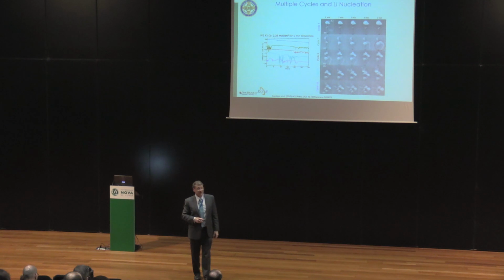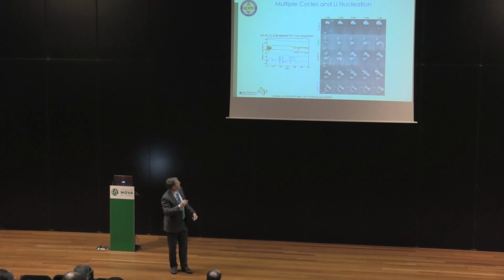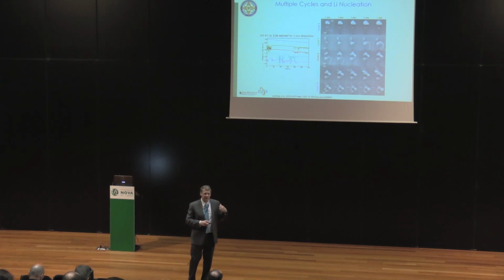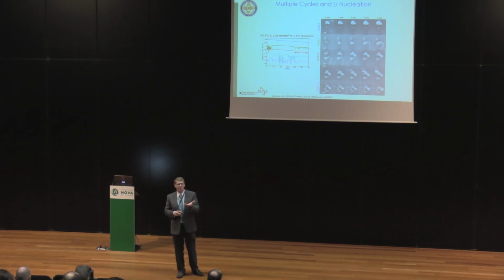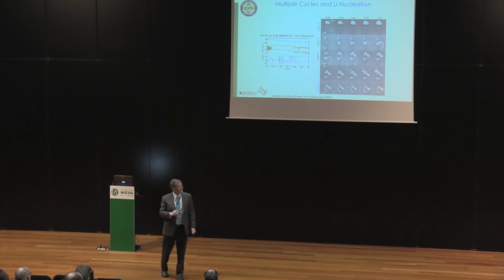Well, there's actually a good news story in these images, right? So here's that one particular dendrite. Looks a little bit like a grasshopper leg or something to me. As they cycle it, you can see at the very next cycle, here's that dendrite. It's still there, so that means it's electronically isolated from the anode, but it slowly dissolves away as they continue to plate. So that's actually good news, right? That means that dendrites that you're forming, this lost material, or no longer electronically active material, is being dissolved back into the electrolyte during the cycling. So that's a positive. That means that you are actually going to get back that material, or get back that lithium, right? So there you go, it's gone.